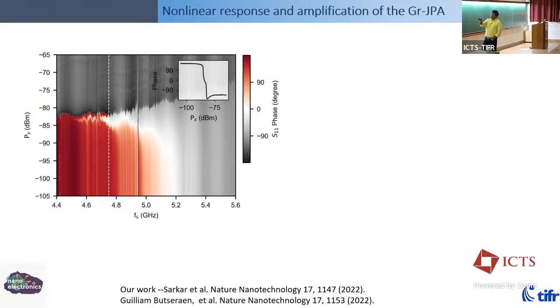And if you sit at a particular gate voltage, as you increase the pump power, you will see that it bends to the left. And that's basically because this cubic term is softening or reducing the frequency. And when you reach way beyond, you go into an unstable state of the amplifier. But right here it provides the largest gain. And so that's where we sit.